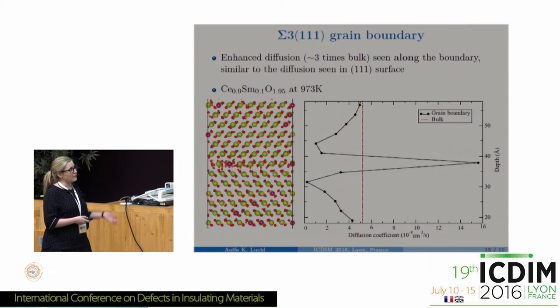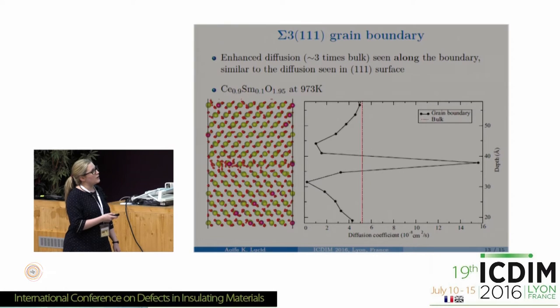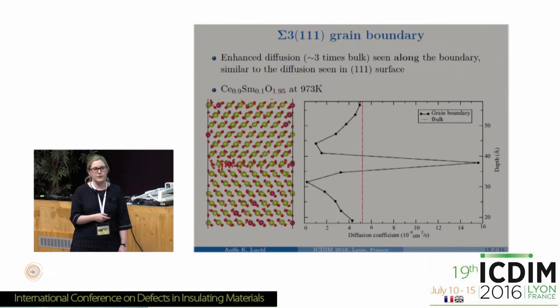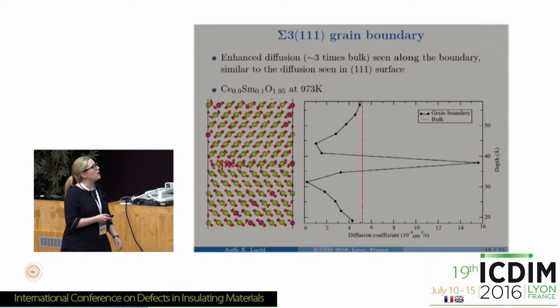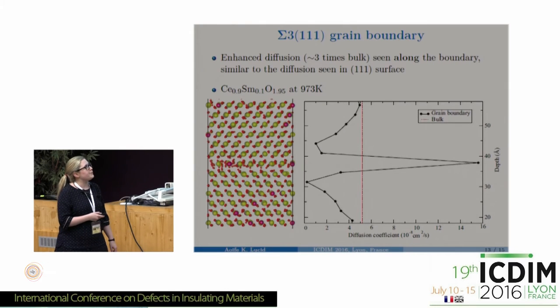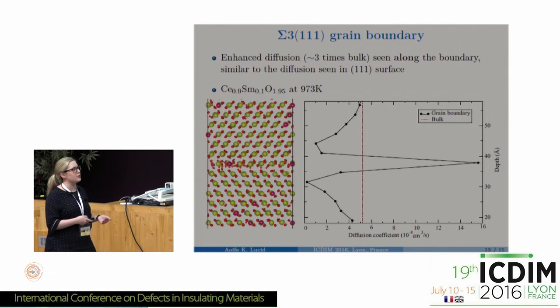It is theorised that because of these depleted layers, diffusion across the grain boundary will be severely impeded as vacancies will find it very difficult to travel across. Planar diffusion shows similar behaviour to the 1-1-1 surface: very high diffusion coefficient along the boundary, roughly the same increase as seen at the surface relative to bulk, and a massive drop in diffusion coefficient in the surrounding layers where there is a large depletion of oxygen vacancies. Perpendicular diffusion has not yet been measured.